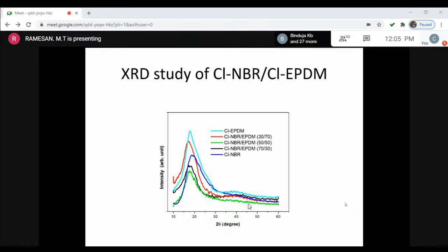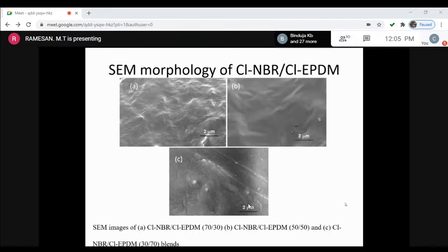And this is some morphology, and you can see that the first one is the 70-30 system. You can see some bump type projections in that system. Whereas in the case of the 50-50 blend ratio, there is a uniform morphology, which is a clear indication of the formation of a miscible polymer blend system, and at the 30-70 ratio the morphology changes slightly into an agglomerated or irregular structure. So this means that the 50-50 blend is good for this system.